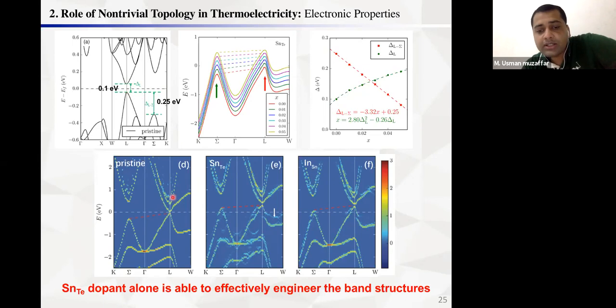So then we unfolded the band structure. Actually, when we do the doping, we need to construct the superstructures, supercells. So to directly compare the anti-site doped band structure with the pristine case, we unfolded the band structure. If we compare the pristine case SnTe and the anti-site doped case, you can see there appears an extra band. In the pristine case there is no band here, but in the anti-site doped case, there appeared a band. So this band corresponds to the resonance level, as I mentioned previously.